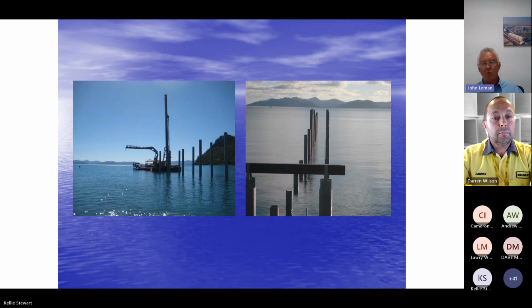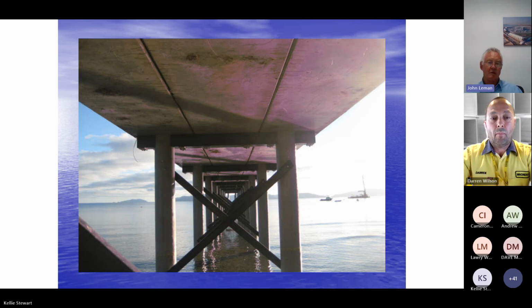Some of those inshore ones you can see are low because there was a little soft spot there. So that's where they had to extend the piles, and that worked well also. So that's just the completed jetty looking underneath it out to sea. You can see there's three deck slabs there. That was purely driven by what the piling contractor could lift and put into place, because they're pretty thick slabs. But you've got the fiberglass FRP piles, the FRP headstocks that are all bolted within the system, and then the FRP cross bracing with the stainless steel bolts going through the piles to tie them together.